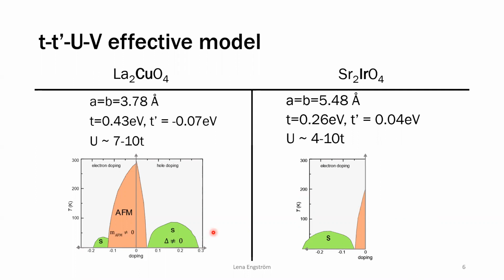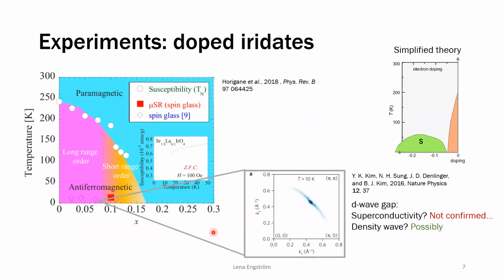Now, why this simplest prediction has some problems is when we actually look at when it has been doped with electrons. So after this prediction had been made, chronologically, there have been experiments with doping these iridates. And we do see a decreased antiferromagnetic order. But the most promising for anything like superconductivity was done in 2016, where there was some kind of order that had a d-wave gap, which is what you expect from superconductivity in this case.